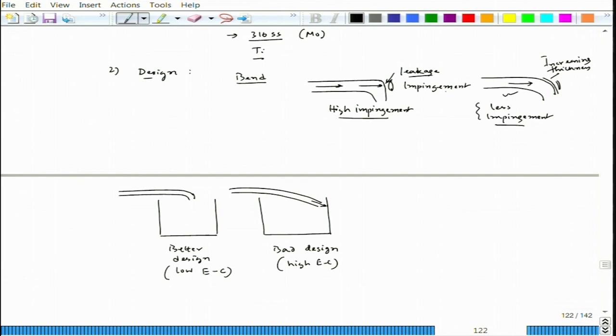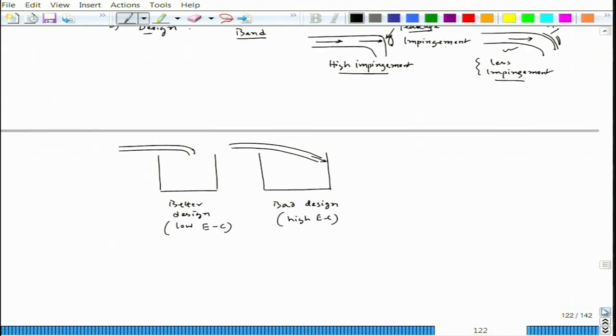Now you could see that the problem comes when some water flow hits the metal object at a very high rate, and that involves impingement, and if we can reduce that impingement, the erosion corrosion can be reduced to a great extent. So, this is another sort of design. Here you are not changing any materials, the only thing is changing the position of water flow, we can reduce erosion corrosion, fine. Now, comes to other aspects, like for example, if you have a tank, and let us say this is a tank and this is the inlet pipe.